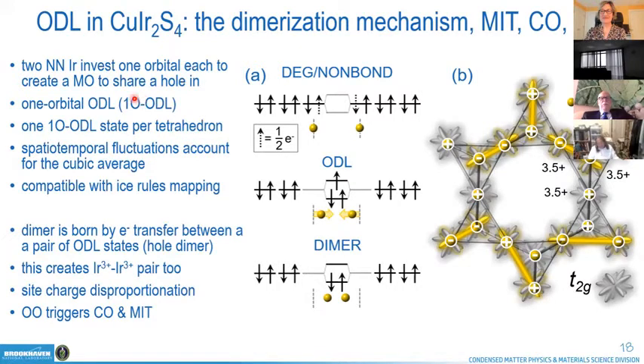So at high temperature in the metallic regime, you have iridiums that are each having half a hole in the triply degenerate T2g manifold, and it's beneficial for the system for pairs of iridiums to invest one of their orbitals to create a molecular orbital type state to share a hole. So there is only one orbital of each iridium involved, and it can form this state in different directions.